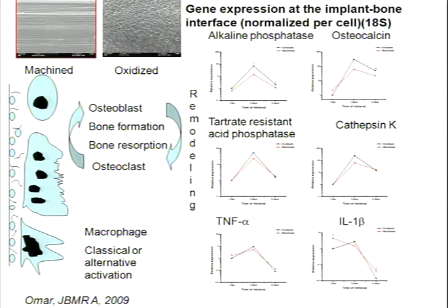However, now comes the thing I alluded to before. Bone resorption, at least denoted as the expression of genes operative in the resorption of bone, they are expressed at the same time, very rapidly. So bone resorption is triggered directly as well. And we have a higher expression of bone resorption in the vicinity of the rougher surface.